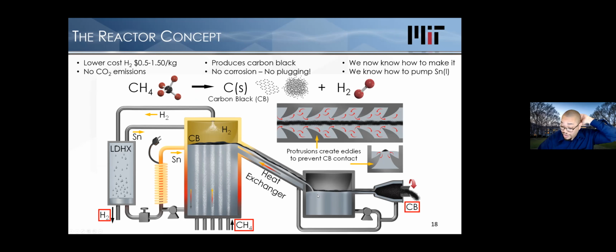What's illustrated here, and these are some of our innovations added to this, is that you can utilize a ramp and have that ramp double as also a heat exchanger, so you can cool the tin and carbon down as it's moving out. Do separation, separate out the carbon, pump the tin back in and keep the tin all in your system. You can also do innovative things like liquid droplet or direct contact heat exchangers, where you bring liquid tin directly into contact with the 1400 degrees C hydrogen to actually do the recuperation and keep all the heat in the system.